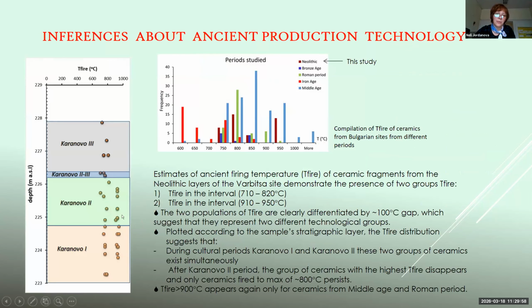So when we plot the obtained firing temperatures along the stratigraphic column, which was provided by the archaeologists, it's seen that during the first stages in Karanovo culture, the two groups of ceramics were existing at the same time, with higher firing temperatures and lower. So we consider this as representing two different technological groups. And it's also interesting that such high firing temperatures are obtained only in ceramics from the Middle Ages or from the Roman period.